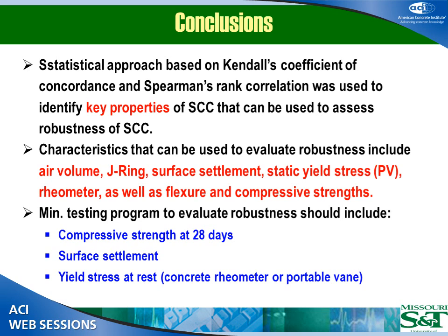And it's always, we see this with the polycarboxylate, you get the stability, but in terms of robustness, they're more sensitive. It does not have to be related to viscosity, because some of them have higher viscosity, some of them have lower. But you're right, as you add more PNS, for example, that can reduce yield stress, but also can increase your viscosity. Thank you very much again, Kamal.